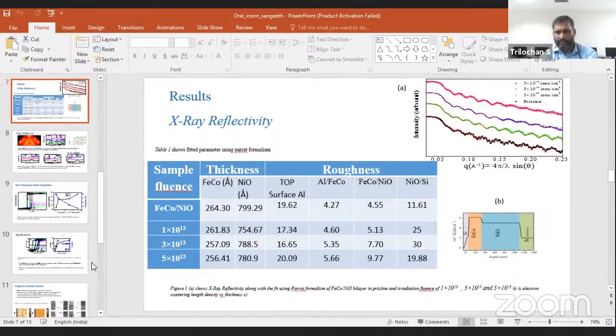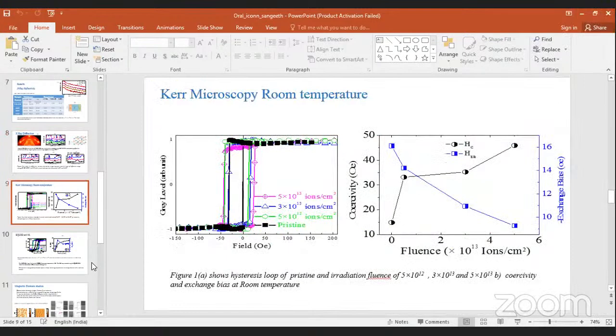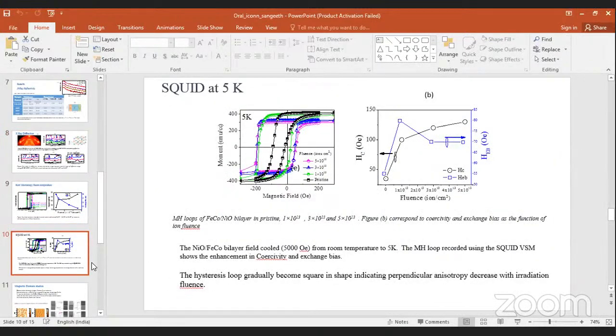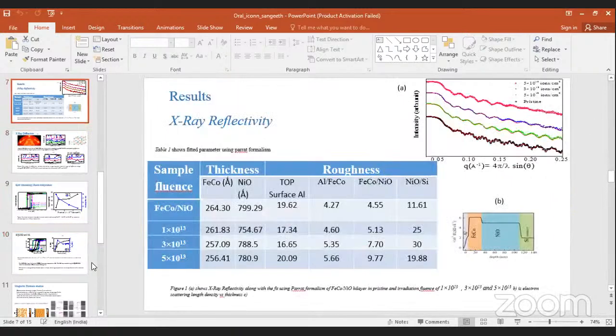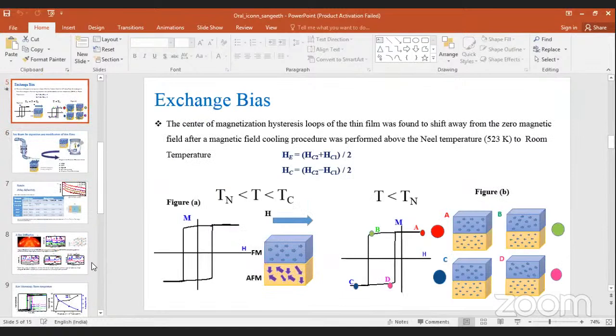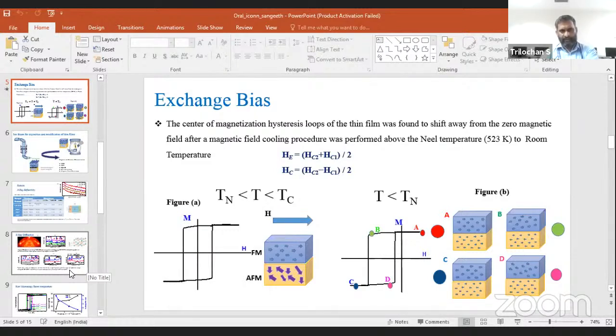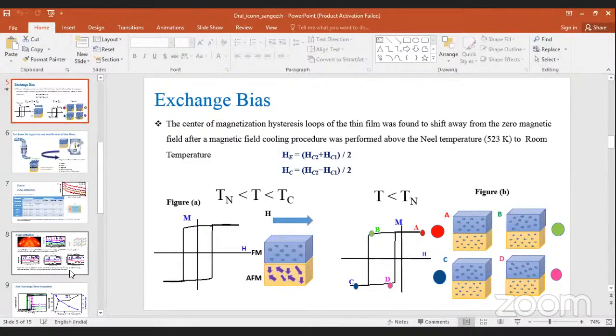There is a question in the chat: how could you calculate the exchange bias from the M-H loop? We can calculate the exchange bias from the hysteresis loop after the field cooling. The formula is the exchange bias equals (HC1 + HC2)/2, where HC1 and HC2 are the coercive fields near zero magnetization. That shift in the hysteresis loop basically represents the exchange bias, how much it shifts along the field axis.